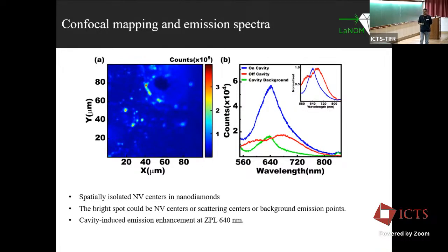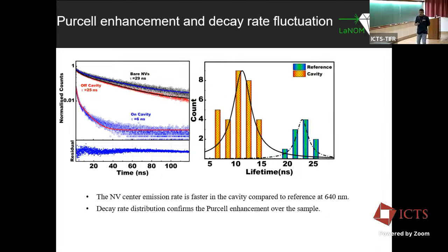So PL spectra confirm that there is a cavity effect, and the actual measurement is a lifetime. The NV, which is 29 nanoseconds in the glass substrates, or in an off cavity sample, reduced to 25 nanoseconds. So when you do our actual sample, you can see that the lifetime or the decay rate become much faster. The lifetime becomes 6 nanoseconds. And this is actually the Purcell effect, where you trap an emitter in an electromagnetic environment and try to modulate its emission properties. Now the question is, do all your NVs behave like that?